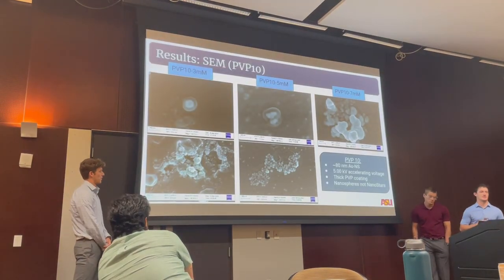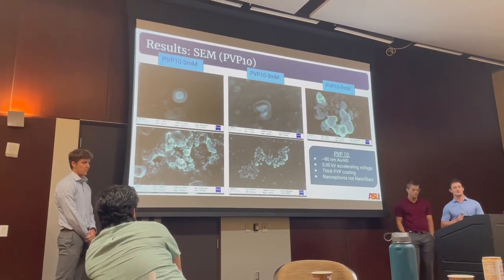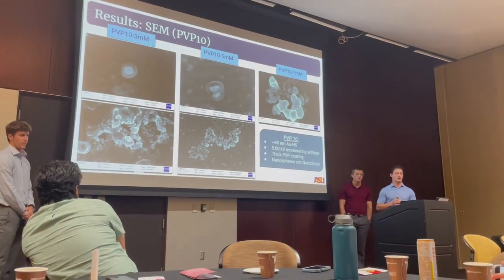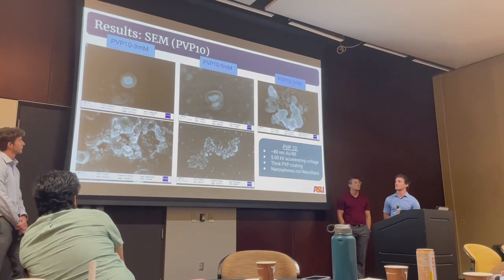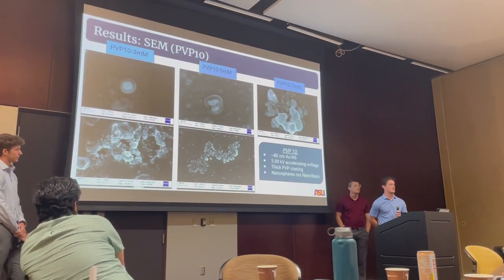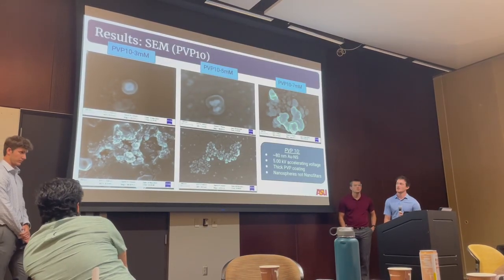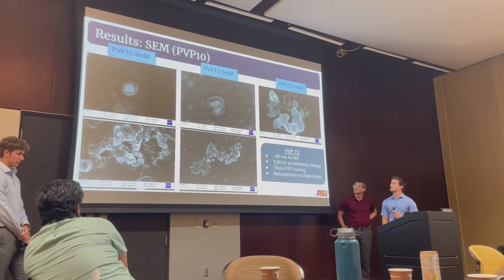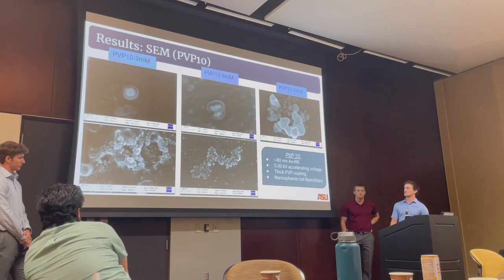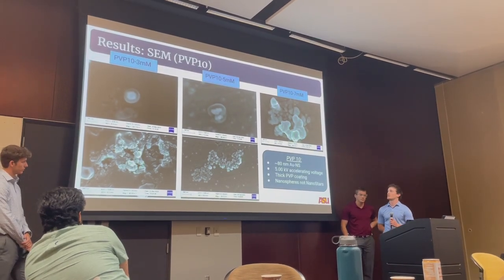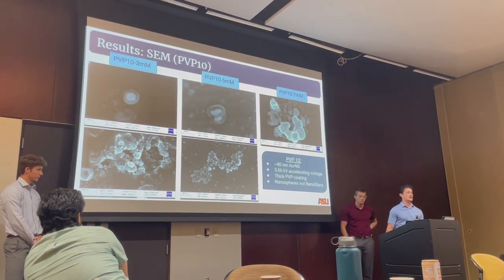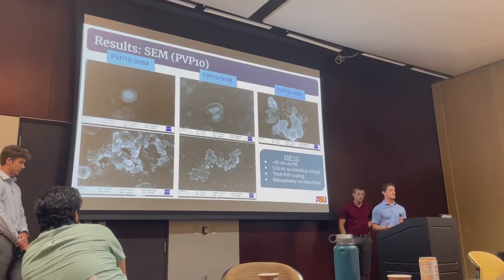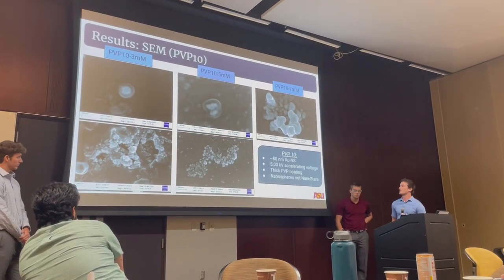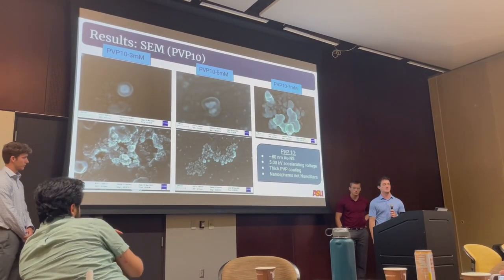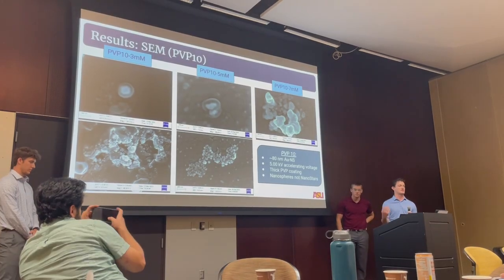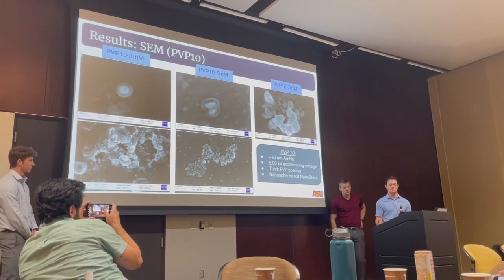So once we had determined with our XRD that we were actually creating gold nanostars, we moved on to scanning electron microscopy to see the imaging, because we wanted to see what type of morphology we had at this point. Starting off with our PVP-10, we got about an 80 nanometer radius of the particles, but we weren't really seeing what we wanted because we didn't have any branching effects. We had more nanospheres rather than nanostars. We also had a very thick PVP coating, which was another concern because that reduces the amount of absorbance they can have inside the body.